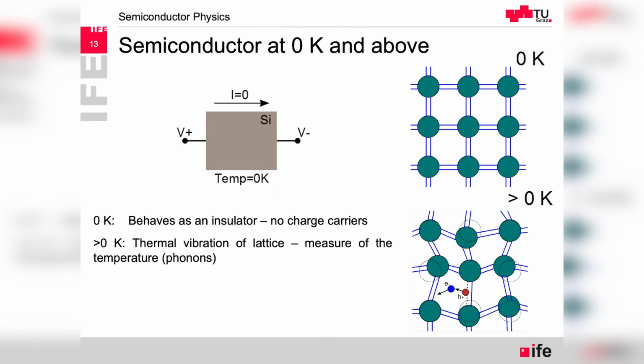So what happens is, for example, for silicon, but also any other material, in fact, for any semiconductor, there will be no charge carriers at 0 Kelvin, but as the temperature increases, and you can see there is this vibration of the lattice, because of that, there will be energy passed from phonons, and the electrons can get the thermal energy and get promoted to the conduction band.